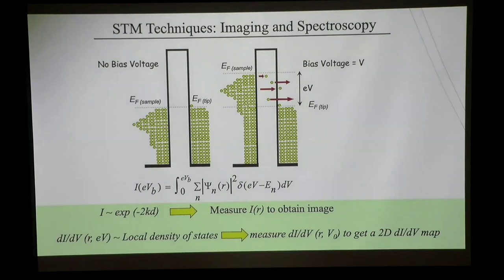And so because of this, you can also show that the tunnel current is exponentially sensitive to the distance between the tip and the sample. And that gives us the ability to get atomic scale images. The dI/dV differential conductance is proportional to this object, which is the density of states, which is the number of states per unit energy. So this is what we can measure with the STM.